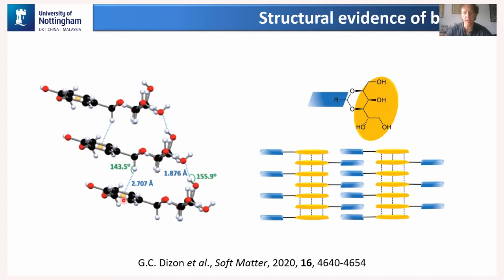Here's the aromatic group that comes off the side of the sorbitol group here, so that's the R group here. And then these hydroxyl groups, the oxygen atoms are in red, and you can see that there are hydrogen bonds joining up these molecules, and they form a kind of chain in the crystal structure. So this is not a gel, this is a crystal structure. This molecule doesn't actually form a gel, but it gives us an idea of how they come together. We can check that by infrared spectroscopy. What you also see is the hydrogen atom that's attached to the acetal carbon atom here is actually forming an interaction with the pi surface of a neighboring aromatic moiety on a neighboring molecule there.